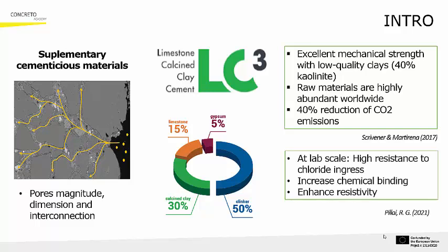In terms of durability, at lab scale, LC3 concrete has already proven a high resistance to chloride ingress, an increased chloride chemical binding, and an enhanced resistivity. These results reflect how LC3 refines the pore matrix through a synergistic reaction between its three main components.